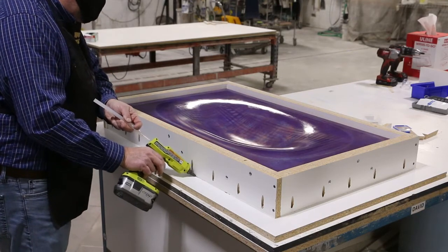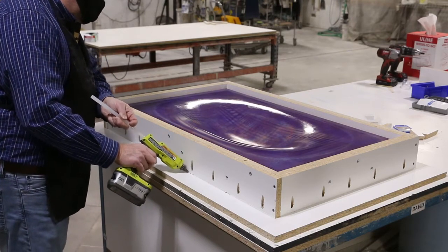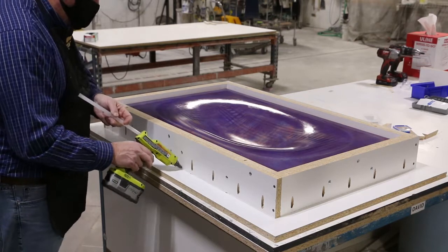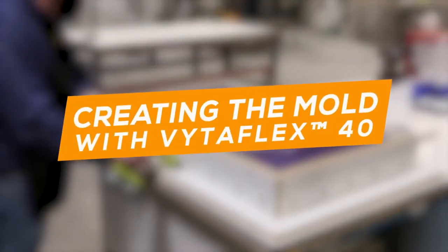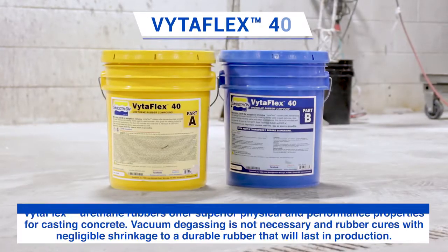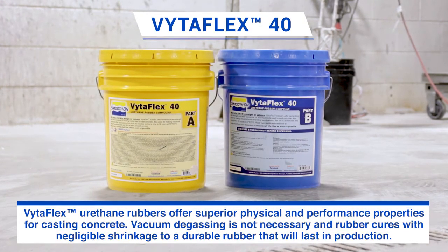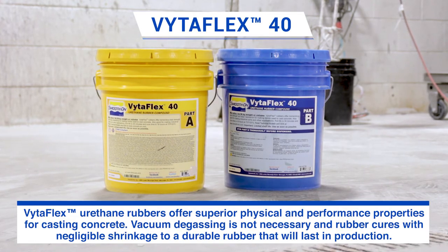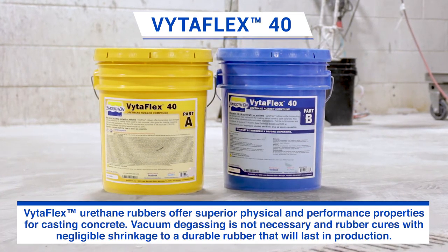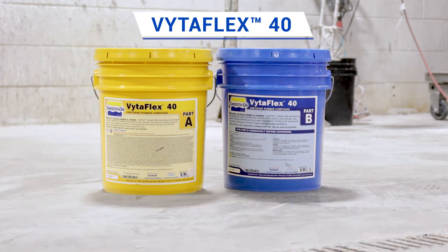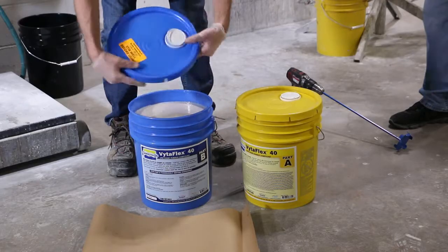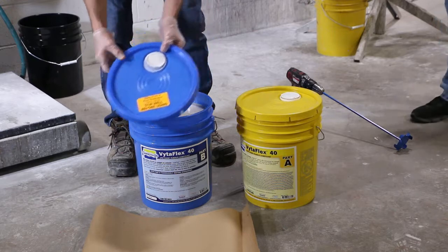Seal the perimeter bottom with hot melt glue to prevent liquid urethane rubber from leaking out of the box. I chose VytaFlex 40 urethane mold rubber for this project because the mold box will offer dimensional support and the 40 durometer will allow easy demolding of the 4-inch high sidewalls. Begin by pre-mixing part B to be sure no components have settled.